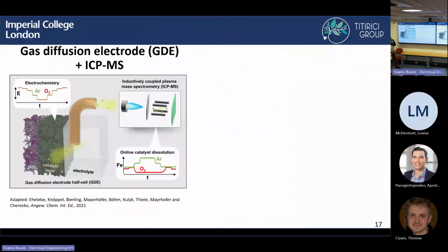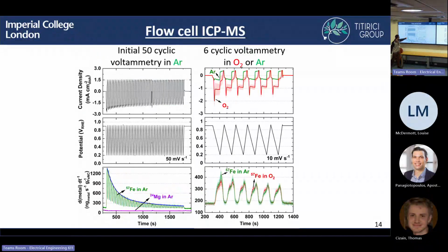Basically, in the flow cell, we did 50 CVs in argon, and we see there's this exponential decay where there seems to be some unstable iron species. So then we said, okay, in the GDE we'll do the same protocol because we see there seems to be some unstable species. They didn't measure the ICP-MS during the 50 CVs initially in the GDE, mainly because the concentration was so high that you hit the limit of the detector. The reason why we didn't show the measurements in argon at 75 degrees is the iron concentration was so high it was above the limit, and you can't run the measurement.